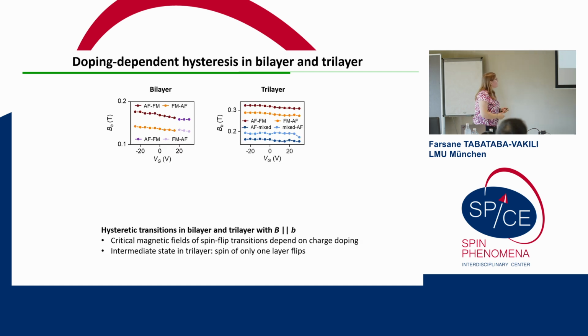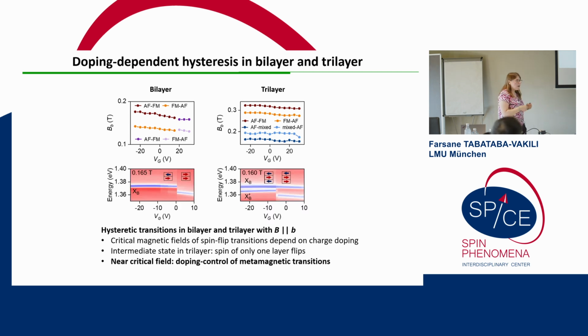So plotted here is the critical magnetic field as a function of gate voltage. And now if we cross this line horizontally, so if we dope at a given magnetic field, we can also induce this metamagnetic transition quasi-electrostatically. So here this is shown in the bilayer. If we're at 165 millitesla, we then apply doping, and we see here this jump in exciton energy at around 0 volts, where we have this change in the magnetic order. And in the trilayer here, this is shown for the antiferromagnetic to intermediate state transition. So this is just kind of neat. So we have a kind of one-way electromagnetic switch.